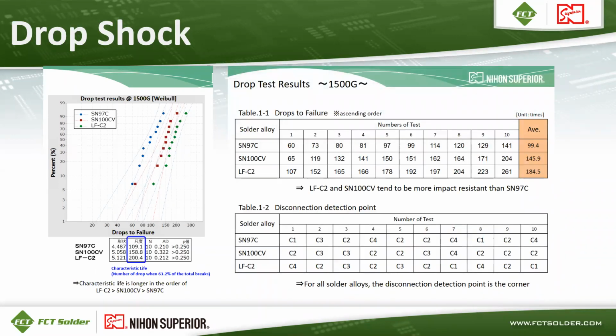Here are the numbers of tests for the results. You can see SAC 305, which is otherwise known as SN97C, has 99 drops to failure average. SN100CV had 146 drops to failure average, and then LFC2 had 184 drops to failure average. You can look at the detection disconnection points at the bottom in that table, and those points are all at the corners of those BGAs, which makes sense. That's where the stress is the highest, and that's where those solder joints are going to fail first.